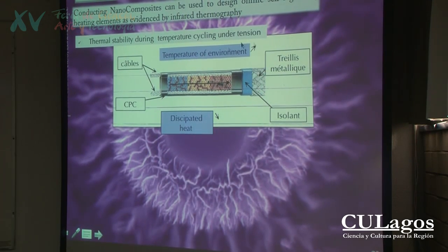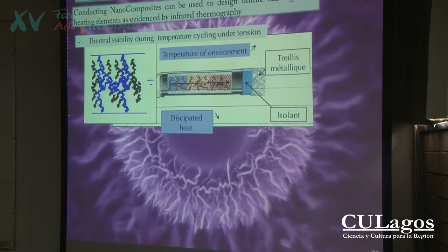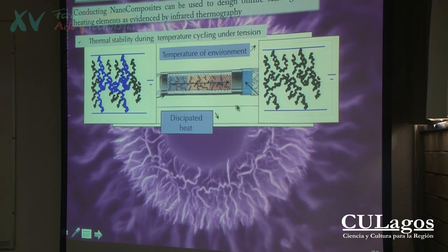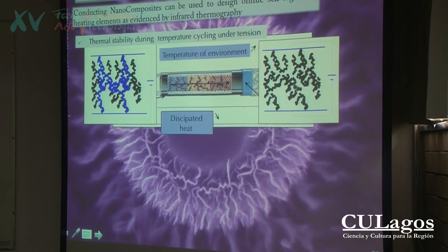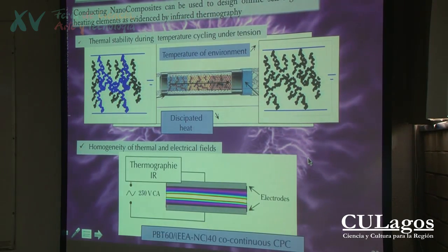You can also design heating device to produce heat from current, but not only that, you can design your systems so that the temperature will be controlled automatically without any electronic device. Because in the composite there will be nano switches that will disconnect themselves if the temperature is increasing. So at the nanoscale, increasing the temperature will result in the disconnection of the conductive networks upon temperature. On this figure you can see that when you apply current to the two conductors, the nanocomposite is heating, and you have a gradient of temperature between the two wires. And then the temperature can be automatically adjusted.